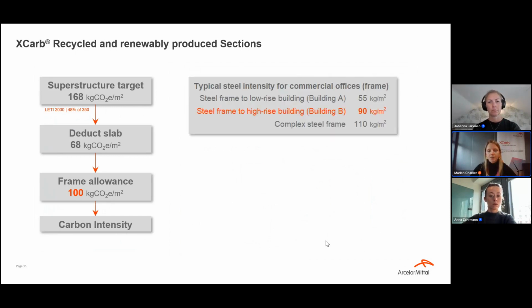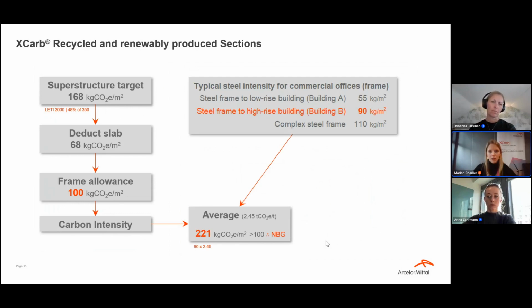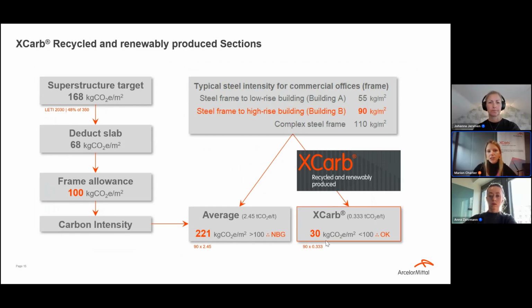So now we look at the carbon intensity. If once more we take an office building as an example, we see that, of course, depending on the height of the building, we will have a different steel intensity. So as an example, we can take the steel frame of a high-rise building where we have roughly 90 kilos of steel per meter square. So now we have several possibilities in terms of carbon intensity, either with an average. Here we have roughly 2.5 tons of CO2 equivalent per ton of steel, which is what we have, for example, for the blast furnace route, or as an average in some parts of the world. And then we would end up with 221 kilos of CO2 equivalent per meter square, which is above the target that we have. But now if we use the xcarb recycled and renewably produced steel, because the carbon intensity factor is much lower, we reach a much lower number, which is actually way below our target. So we're okay with that.